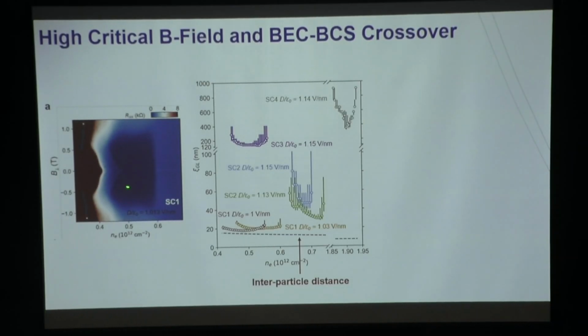So based on that critical magnetic field, you can extract a coherence length based on the calculation of the magnetic flux. You get something on the order of 20 nanometers. You can think that's how big your Cooper pair is. And you can also plot the inter-electron distance at the given charge density, right? That's this dashed line here.